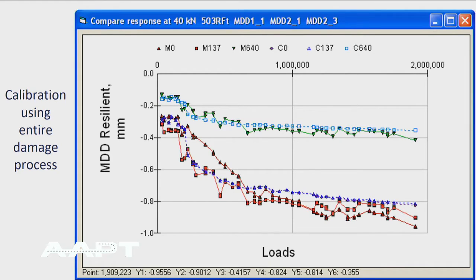Okay. So in this, the red values are the measured values, and this shows the deflections at the top on the surface of the asphalt, and then the other two show the deflections at the top of the base and the deflections at the top of the subgrade for an example test section. So every one of those is a data acquisition point through the entire life of one test section. What we then show is the calibrated damage process, where rather than one data point for this test section, from our initial estimates of what will happen in the first year and then taking that out to the end state with Miner's law, we're fitting that entire curve of the damage process. And then we do the same thing once we've got the damage process nailed down. We take the development of cracking from the initial cracks and then through the progression of cracking as a second model.